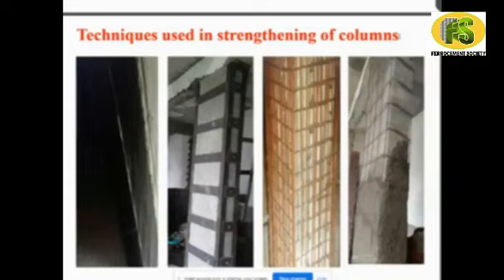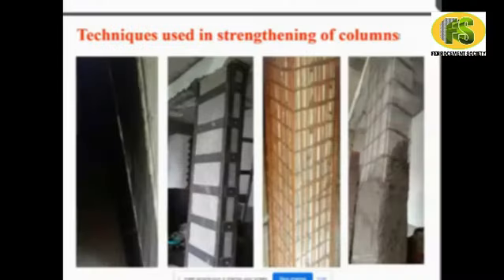Because the kind of NDT they have done after that may mislead the results, because that testing is not for the total combined effect of that column or the beam, including the whole structure. It may give results only for the outer ferrocement jacket, which is certainly stronger than the old component. So, how do we ensure the increase in strength after jacketing while designing?